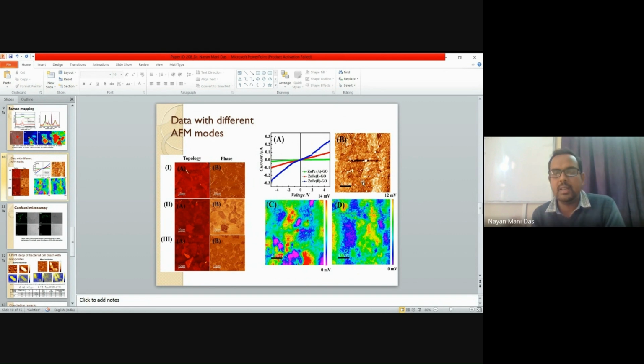We did the electrical characterizations also, and the electrical mapping, with the help of this AFM tip. So this shows that the prominent interaction sites were arising when we did the heating of our composite material. So this shows that this material could be very efficiently used for different electron withdrawing or charge assimilation applications.